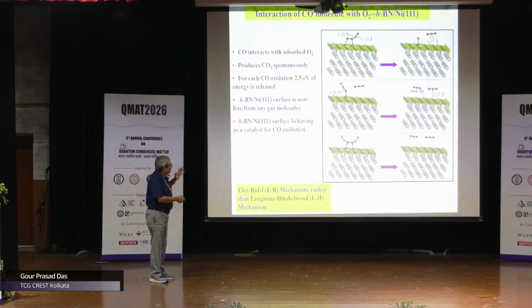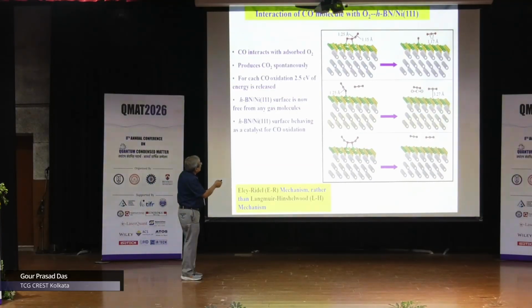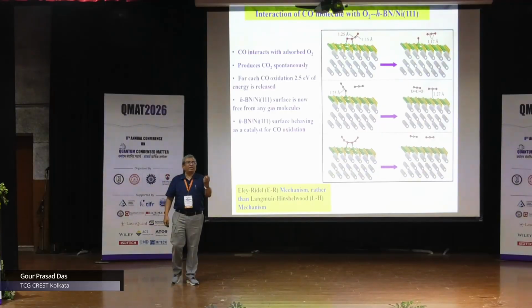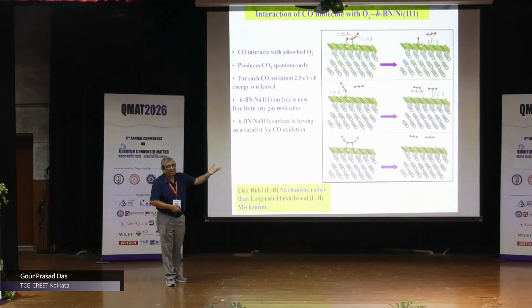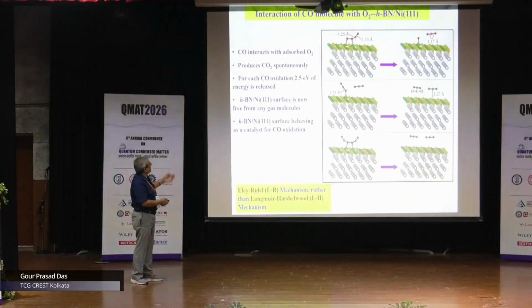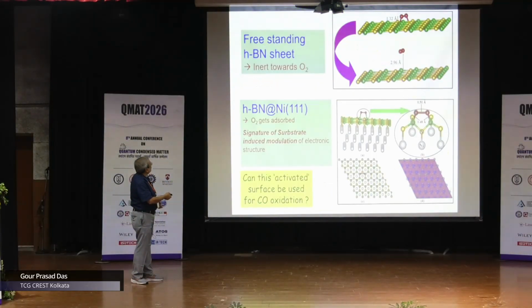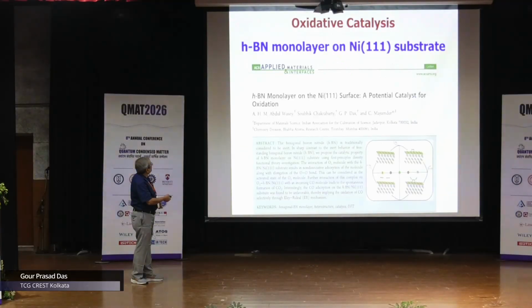So the moral of the story is that when you put this hexagonal boron nitride onto nickel 111, an interface is created. And that interface has a charge transfer. Because of the charge transfer, the ionicity of the boron and nitrogen gets changed. And that is what helps in the catalysis. It's very interesting. Okay, if you are interested, you can have a look at that paper, HBN monolayer on nickel 111.